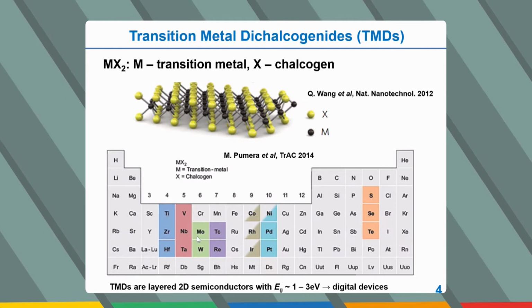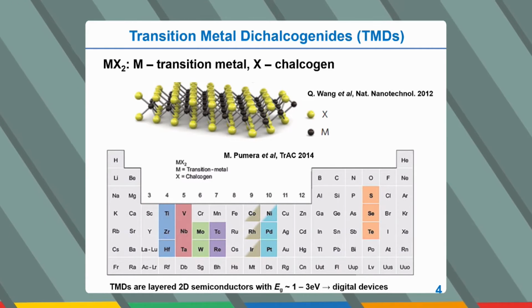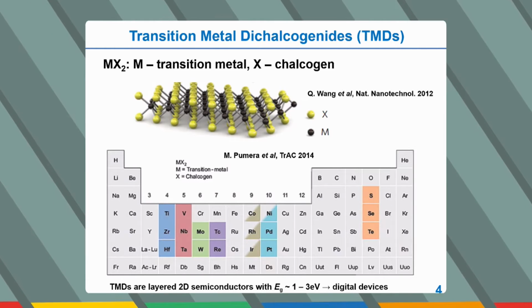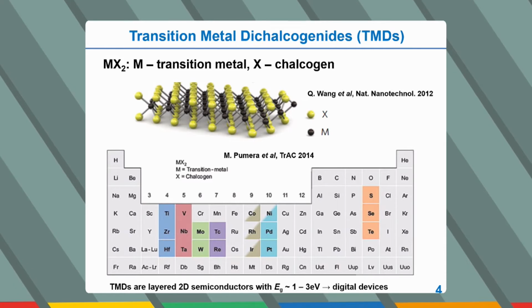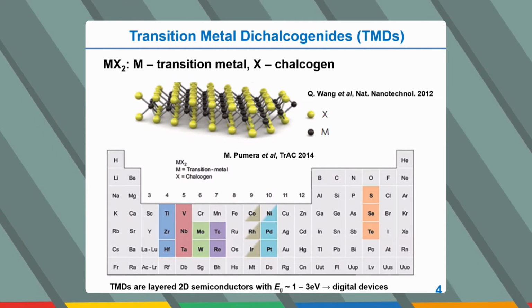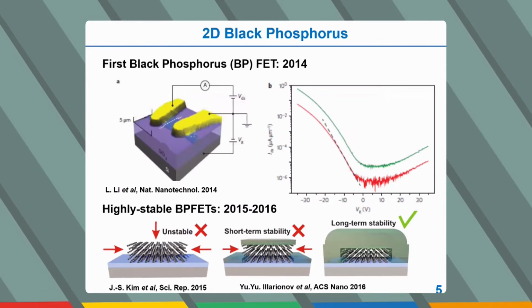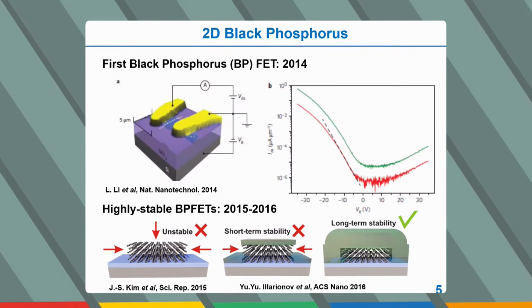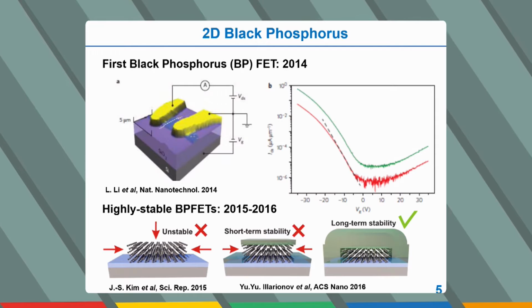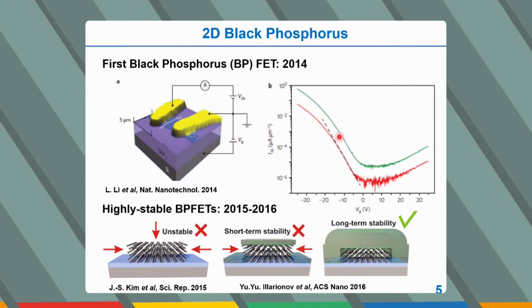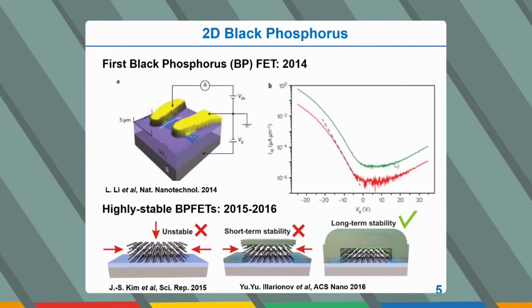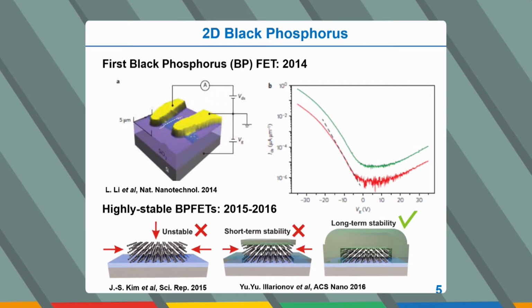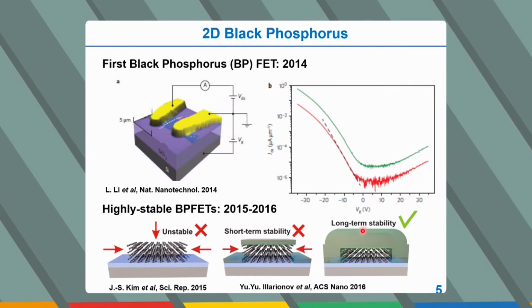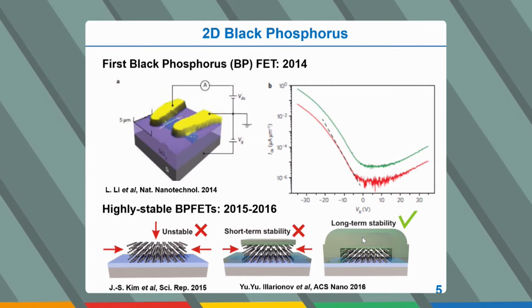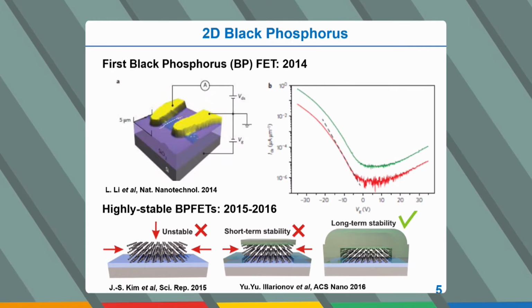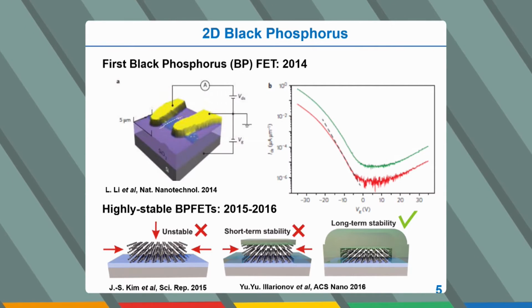So it's transition metals and such elements like chalcogens, like sulfur. And these TMDs already have quite a sizable band gap of 1 to 3 electron volts, and they are very attractive for digital devices because they also exhibit reasonable mobilities. And next 2D materials have been black phosphorus, and this material, in contrast to most TMDs, can enable ambipolar device behavior, so both p-FETs and n-FETs as required for integrated circuits. The only problem was its poor air stability, but in our quite recent study, we addressed this and found that by conformal encapsulation, you can enable long-term stability ranging up to years for these black phosphorus devices.